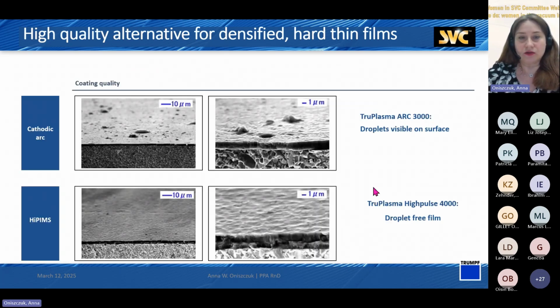Hard and dense coatings you can also get with cathodic arc deposition. However, the problem is that cathodic arc is a bit different technique, where you deliver a lot of power within one spot, and there are effects where you have melting on the target, and you create a lot of droplets, and then these droplets solidify on the surface, leading to microparticles, which can, for example, fall off and lead to a lack of corrosion resistance, and also to a very rough surface. With HiPIMS, you can obtain very good smoothness, good density of the coating, and very good properties of the coating.